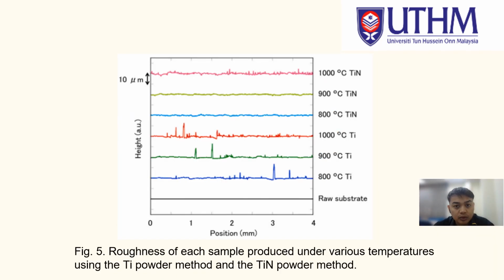Figure 5 shows the roughness of each sample produced under various temperatures using the Ti powder method and the TiN powder method, and shows the roughness curve of each sample, summarized in table 1. All roughness curves of the Ti powder method exhibit some peaks, and the heights of the peaks were on the order of several micrometers. They evidence the existence of Ti columnar grains, as shown in the SEM image later in figure 6.